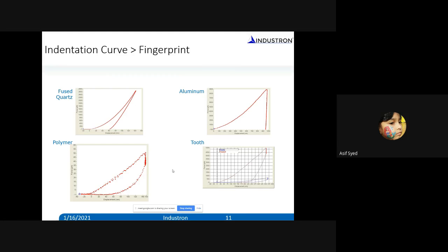For example, if you do it on fused quartz, you will have a response something like that. You have an elastoplastic deformation, and then when you unload, there is some kind of recovery. Whereas when you do the same experiment on aluminum, you don't see much of a recovery. It's highly plastic. So there is a difference between the load displacement curves of fused quartz and aluminum.